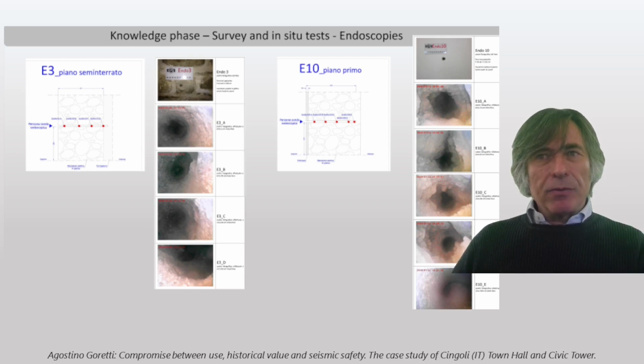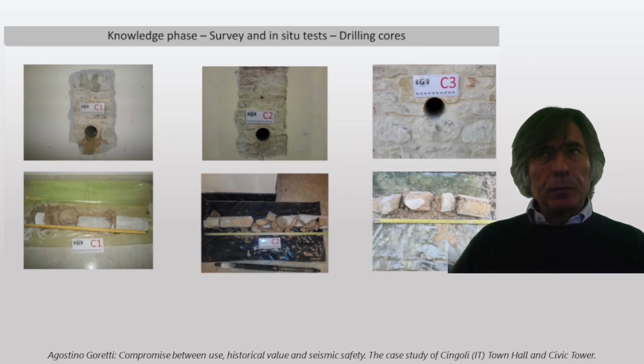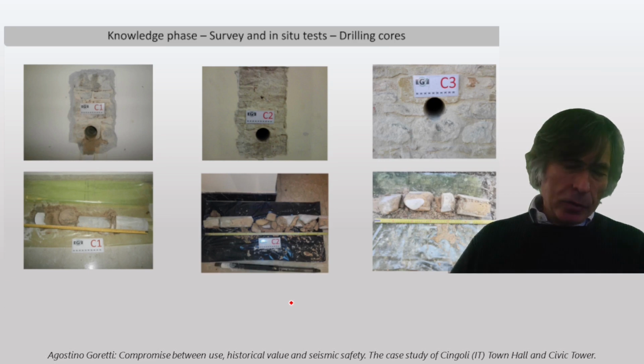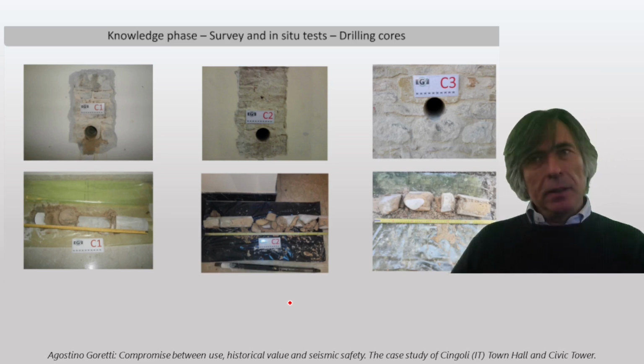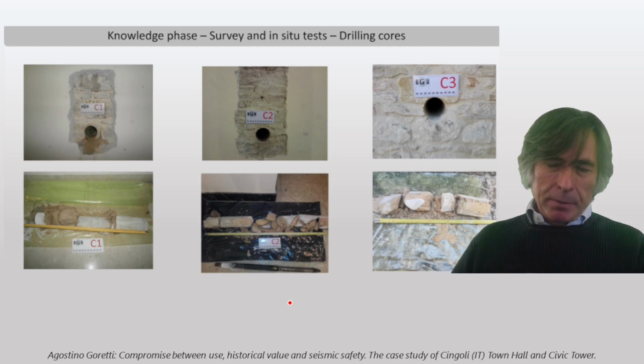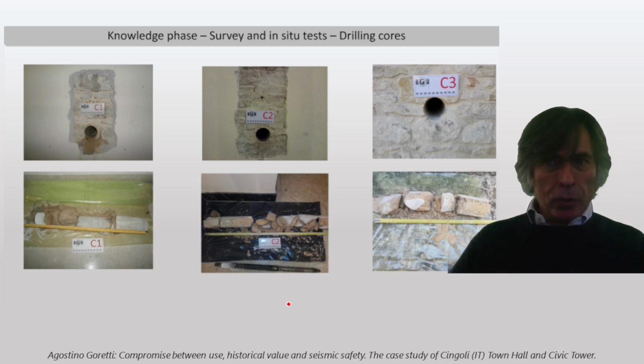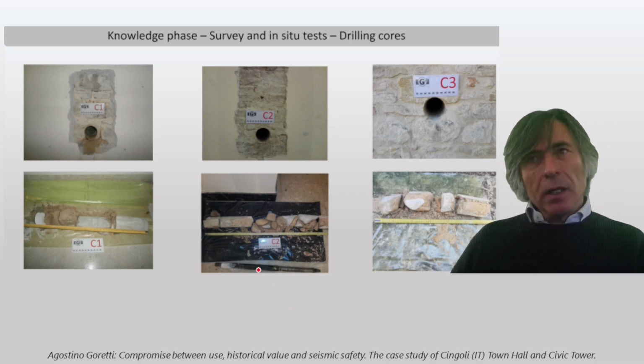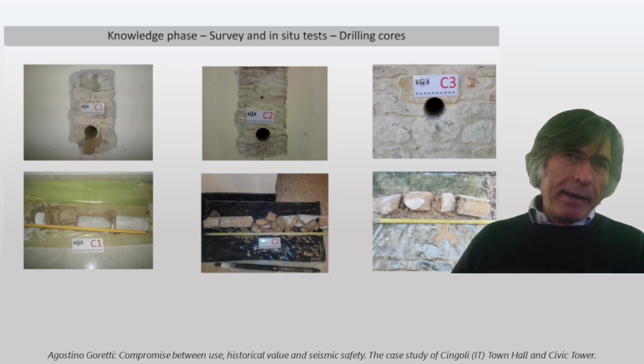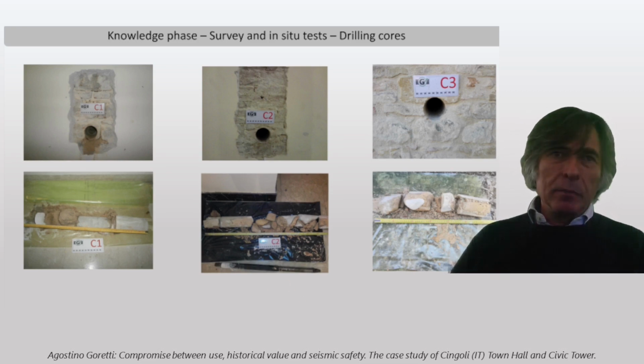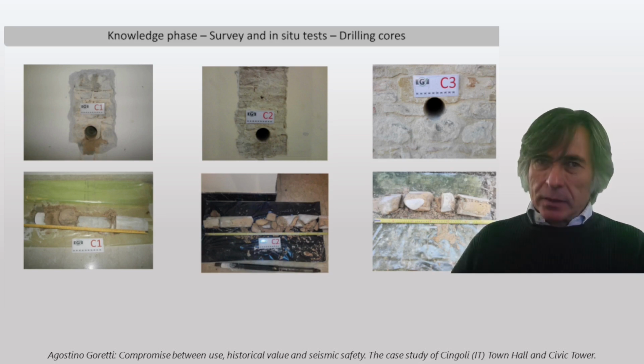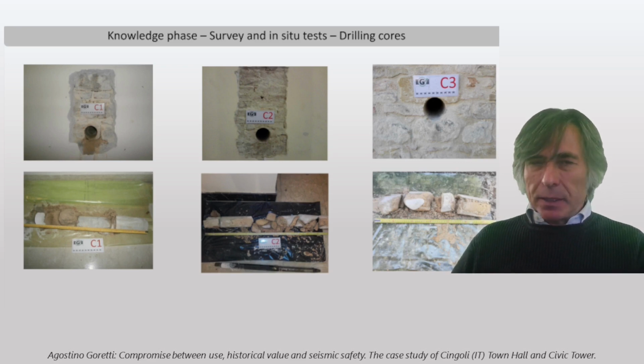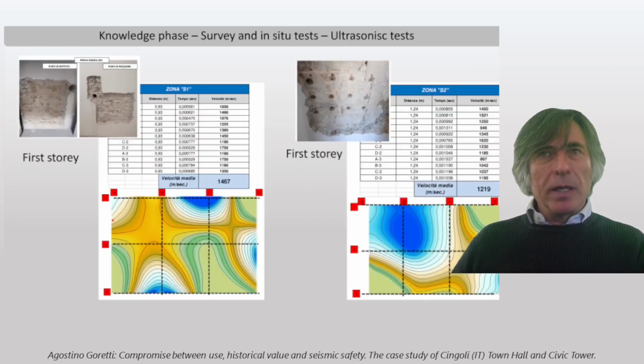But in this case we found from endoscopy, and also from the cores that we extracted, we made not so many cores, just 3 in the buildings, but many more endoscopies, which are less intrusive. We found out that basically the quality of the mortar is more or less the same across the thickness. So it's not made by two layers, the so-called a sacco masonry, with loose material inside, but it's more or less homogeneous.